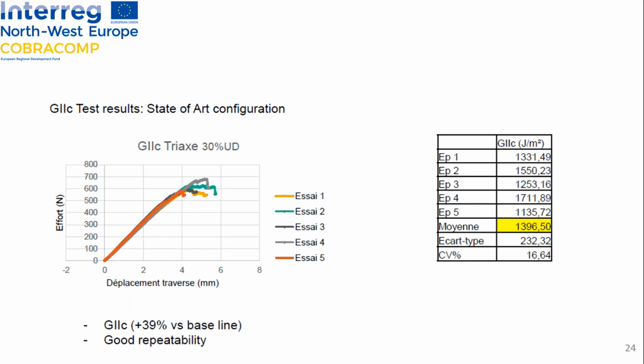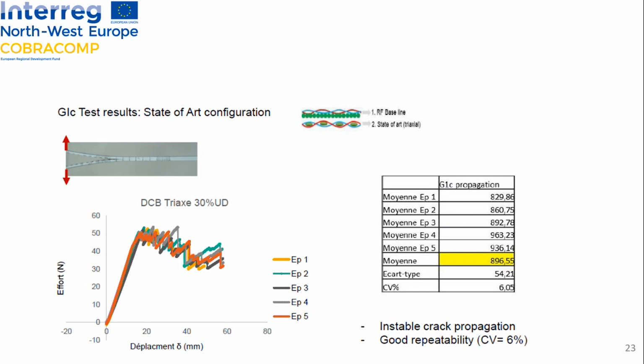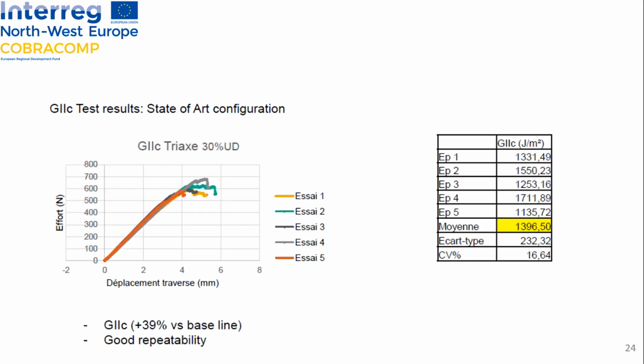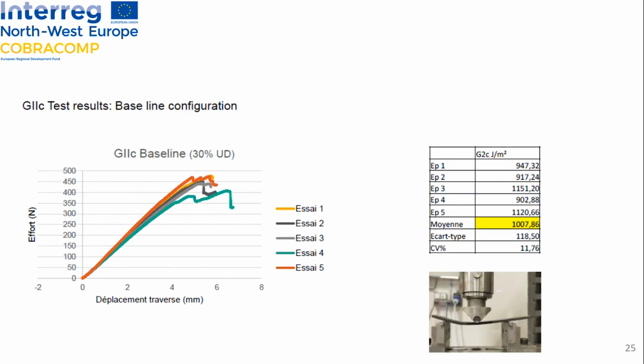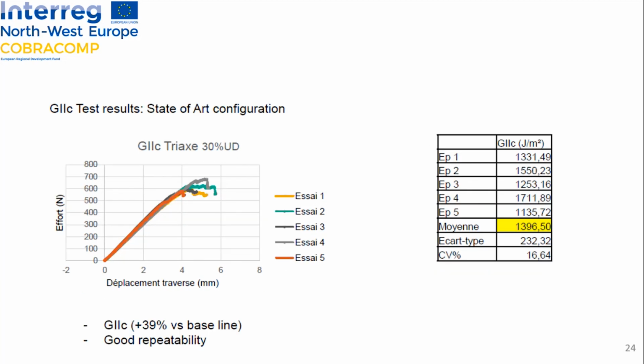For the G2C results, for the baseline, we reach a value close to 1000 joules per square meter, and if we compare the G2C results of the braid samples, it is 39% better compared with the baseline, and we obtain this result with a good repeatability.